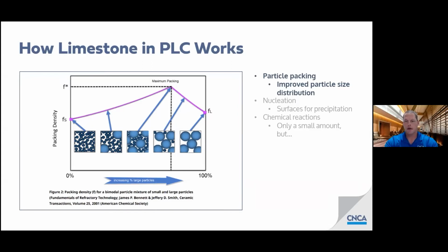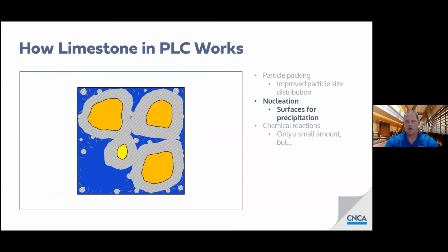And Portland limestone cement, by virtue of the limestone particles being much smaller than the cement particles, are able to pack into those spaces in between cement particles and give us a higher density paste in the concrete, which helps to maximize the density in there and minimize the void space in the concrete. Additionally, we create more nucleation sites for the formation of the calcium silicate hydrate crystals that are the product of the pozzolanic and hydraulic action of the cement. This enables the reaction to take place. It begins at more places, and the crystals don't have to bridge as far between cement grains because these limestone particles are in between them.